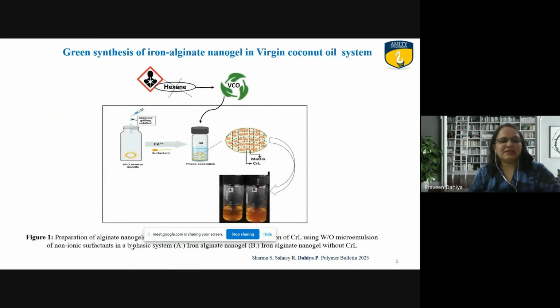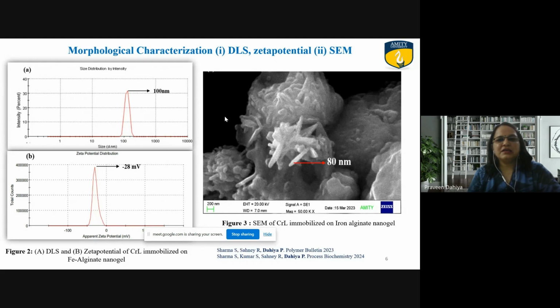Now, moving on to the results. Till now, hexane has been used as an organic phase, and it is due to its optical transparency. But here, in order to synthesize the iron alginate nanogel via a greener approach, the hexane is removed from the system and it is replaced by virgin coconut oil. Rest of the methodology, that is water and oil reverse micelle, is the same. The only thing is that the hexane is replaced by the virgin coconut oil. So green synthesized iron alginate nanogels were developed using water and oil microemulsion method, which is further characterized via DLS, zeta potential, and scanning electron microscopy.